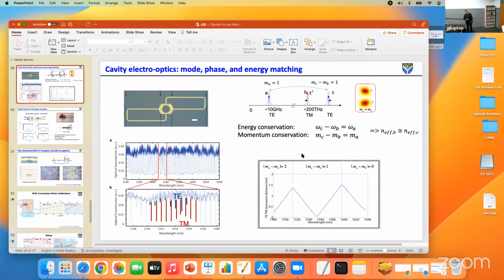Yeah, it's a standing wave, right? So the point of that: if you pull this electrode to this side, just flatten it and put that electrode to that side, that's just a regular half lambda resonator, right? The two ends are plus V and minus V, with 0 in the middle, where you have a maximum current. So when you fold it over, that was really nice. You keep the maximum electric field over here, which allows you to apply this Pockels modulation. The electric field goes that way, and that electric field also goes that way, the same way. So it's like a push-pull modulator configuration. And if you go around the circle, you actually see that your electric field changes by pi. That's very important. You go around the circle, your electric field changes by pi, that gives you angular momentum equal to 1. If the electric field does not change sign, then your angular momentum is 0.